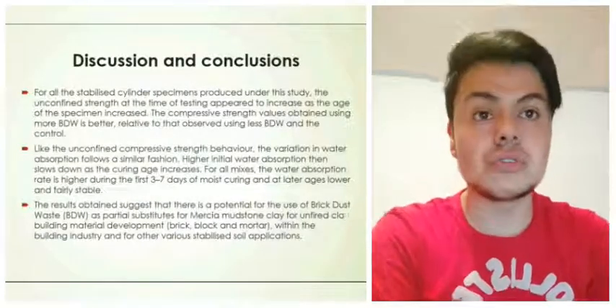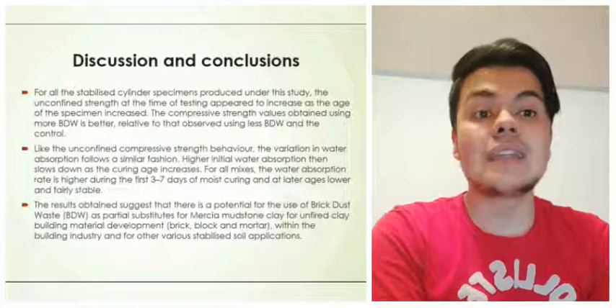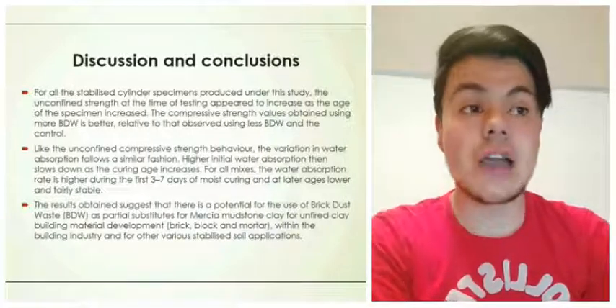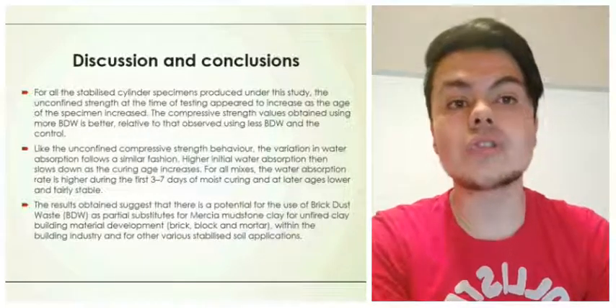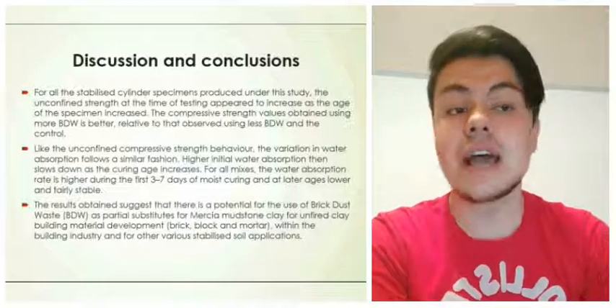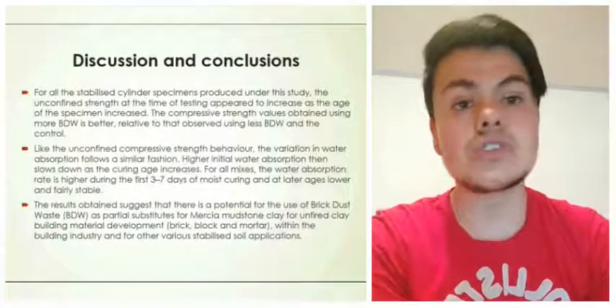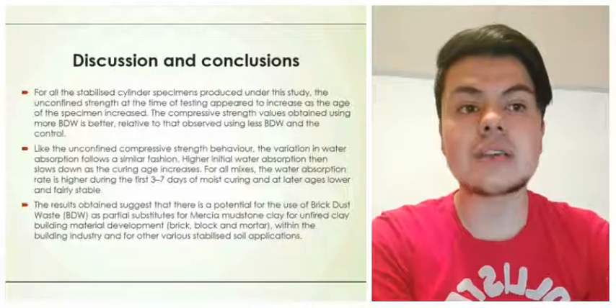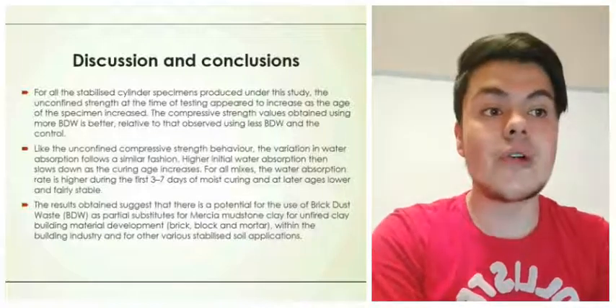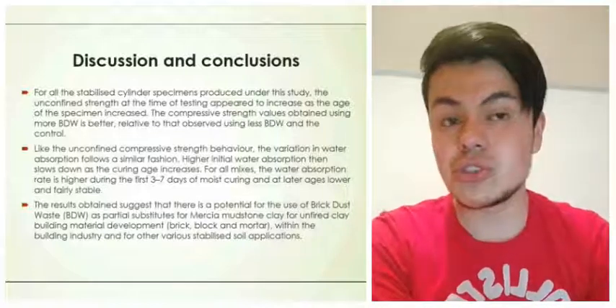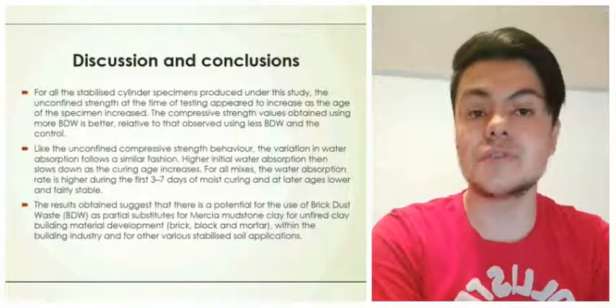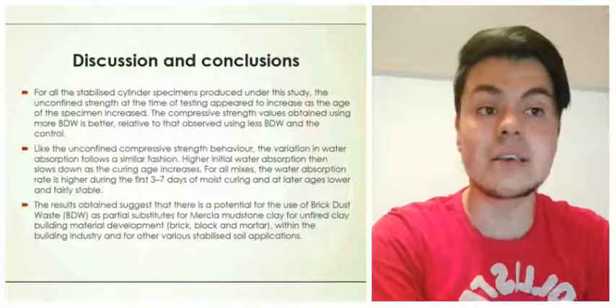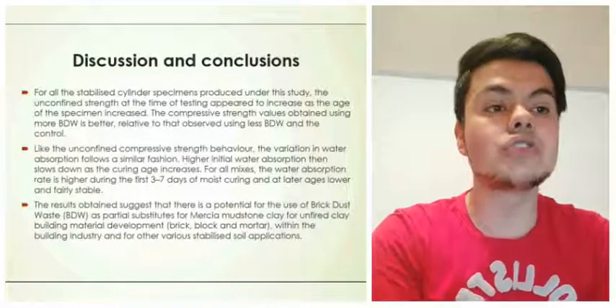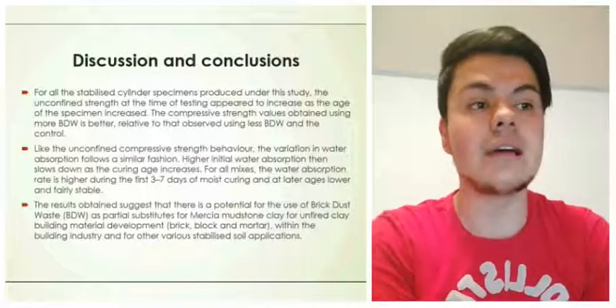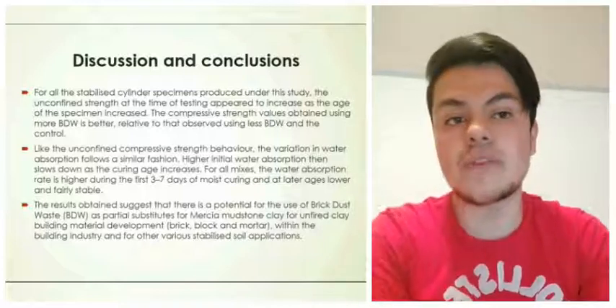Discussions and conclusions. Like the unconfined compressive strength behavior, the variation in water absorption follows a similar fashion. Higher initial water absorption, then slowing down as the curing age increases. For all mixes, the water absorption rate is higher during the first 3-7 days of moist curing and at later age lower and more stable.